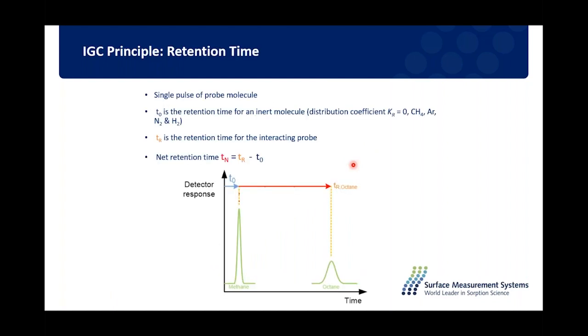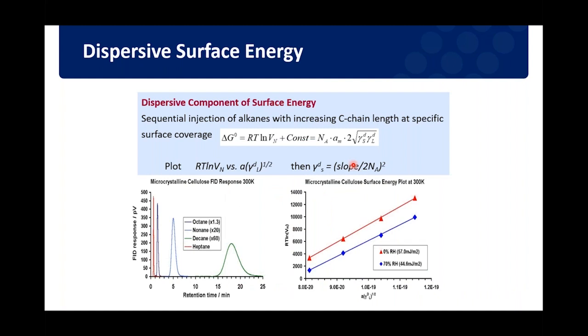As I mentioned, you simply inject different probe molecules, you measure the retention time. From that retention time, I can get the retention volume, which is related to the free energy, and then that gives us access to the surface energy. I won't go into the weeds of all the calculations. We'll be happy to provide that if necessary.